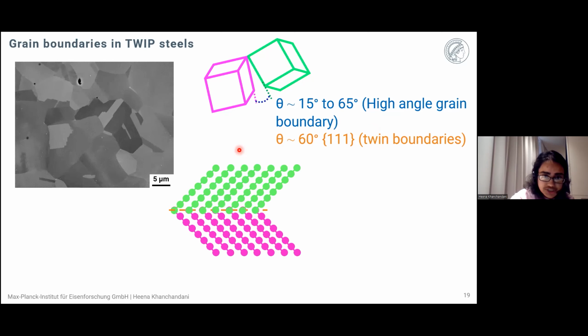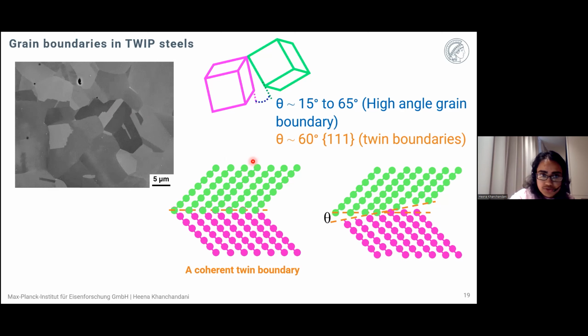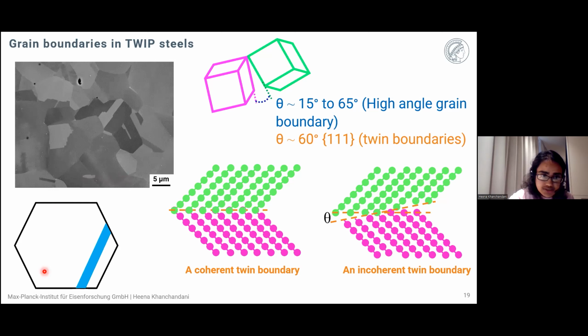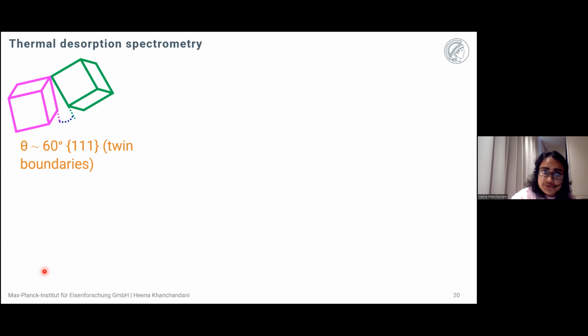Twin boundaries are those which act as a mirror plane between these two grains. And if they have straight structures, such as this one, they are called coherent twin boundaries, while those which do not have a straight structure and are faceted are called incoherent twin boundaries. Now, twin boundaries are specifically important in these materials because when we deform these TWIP steels, deformation twins are formed during deformation and they act as obstacles to dislocation motion, which leads to very high strain hardening and ductility of these materials. So for further study, we first focused on twin boundaries, but not on the deformation twins. We analyzed the annealing twins in the recrystallized material.